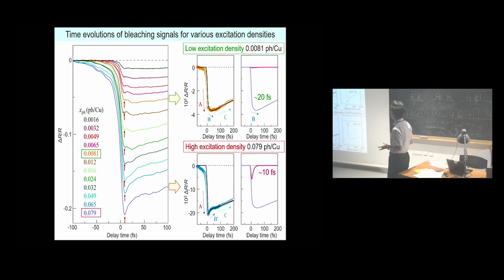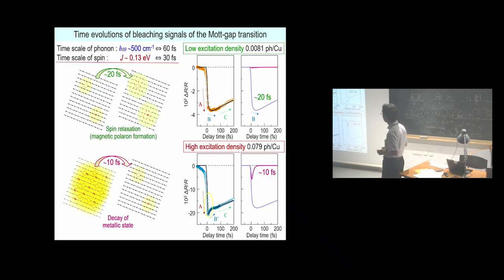Here we plotted the typical time evolutions of the reflectivity for low and high excitation density. For the low excitation density, we can see the rapid decrease of the reflectivity due to the hot carrier generations and the subsequent decrease of the reflectivity labeled as B. By the fitting analysis, we evaluated the time constant of this process B to be about 20 femtoseconds. This time constant is much faster than the time scale of phonons, that is 60 femtoseconds, and that is comparable to the time scale of spin, that is 30 femtoseconds. So this process can be assigned to the spin relaxation processes of carriers, that is the magnetic polaron formation, via the weakening of the antiferromagnetic spin arrangement like this.